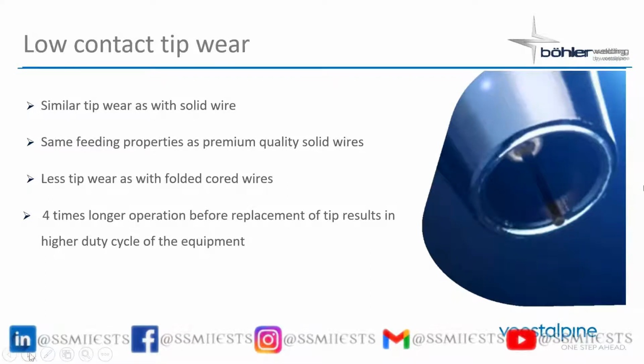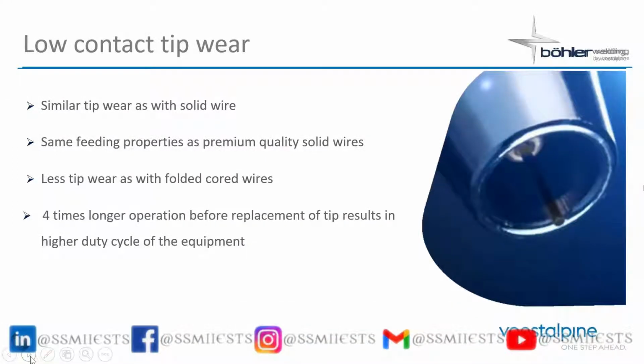So with the seamless wires, another feature that we worked on was the contact tips. Some of you who have done MIG welding in college can understand what I'm talking about. When the wire comes out of the contact tip, there is a likelihood of the tip getting worn out because of the friction. Here, because this is a copper coated wire, and because of the way this wire is manufactured, it's a much stiffer wire. So the tip replacement interval is almost 4 times longer than with a conventional flux cored wire.